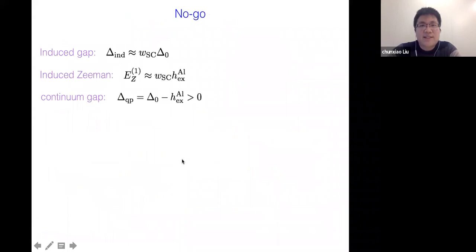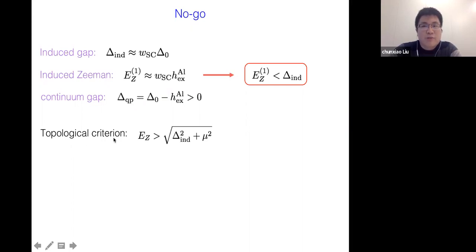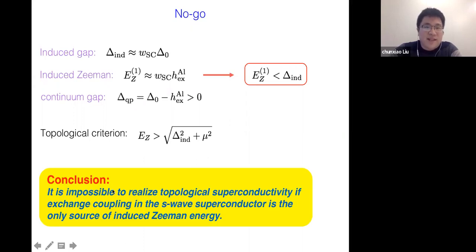Unfortunately, the answer is negative. Because both the induced superconducting gap and the induced Zeeman energy are proportional to the degree of hybridization, the Zeeman energy is always less than the induced superconducting gap if the continuum gap is finite. So the topological criteria can never be satisfied in this case. Thus it's impossible to realize topological superconductor if exchange coupling inside a superconductor is the only source of inducing Zeeman energy. So this is our numerical result, and a more rigorous analytic proof can be found in this paper.